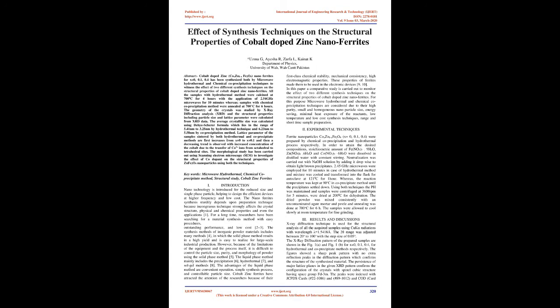The average crystal size was calculated using the Debye-Scherrer formula, which lies in the range of 5.41 nanometers to 3.25 nanometers by the hydrothermal technique and 6.23 nanometers to 5.58 nanometers by the co-precipitation method. The lattice parameter of the samples sintered by both hydrothermal and co-precipitation methods first increases from x equals 0 to x equals 0.1, and then a decreasing trend is observed with increased concentration of cobalt due to the transfer of Co2+ ions from octahedral to tetrahedral sites.